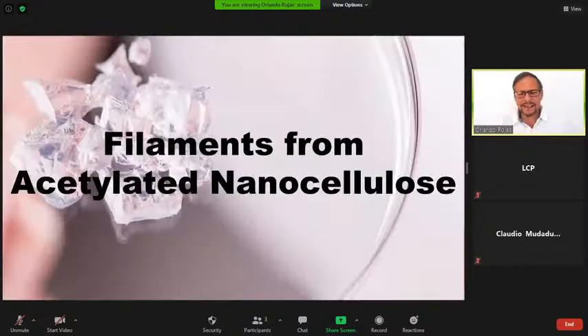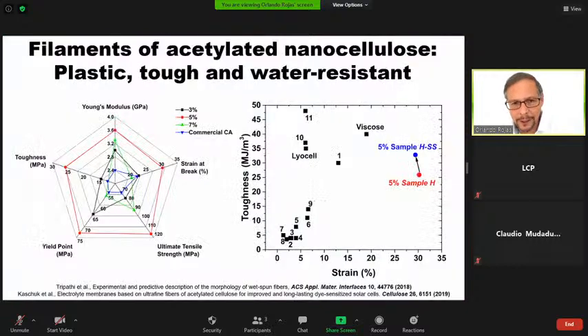If we use acetylated nanocellulose that I introduced earlier, then you can think about the same process, but with a new spectrum of properties. And this is the beauty of having these modifications on nanocellulose, because then we can open new developments as far as the application. So this is a very busy slide, and you can see in the bottom the papers in the area, but in a nutshell, what we want to say here is that this acetylated nanocellulose produces extremely tough materials, meaning that they are strong, but also very extensible.